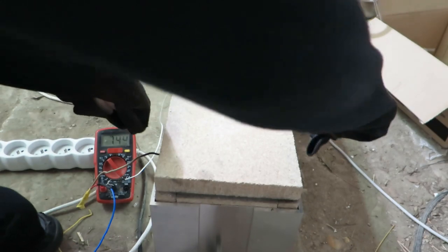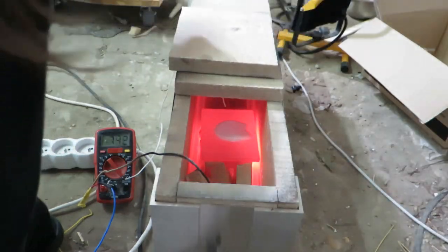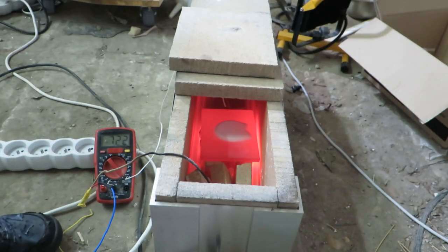Then I baked this at about 800 degrees for three hours. Maybe you can use higher temperature and less time, but I can't test this because my oven doesn't go much higher.